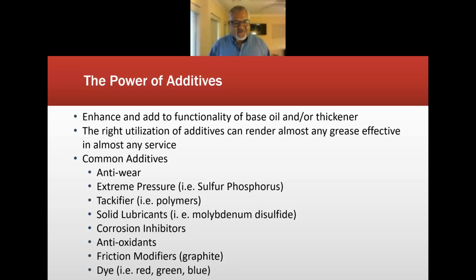Well, you got your extreme pressure sulfur phosphorus. You got tackifiers, polymers. These are used quite a bit in greases, pretty much almost every grease, except for maybe a very fluid straight lithium grease. Solid lubricants, the mollies, typically, or graphites are usually friction modifiers, but sometimes represented as solid lubricants. And in our calcium sulfonate greases, we have calcium carbonates, or the natural form is calcite particles. Those are all solid lubricants. And there's others: corrosion inhibitors, antioxidants, friction modifiers, graphite, and dyes. And we'll never get away from our farmers wanting a red grease.